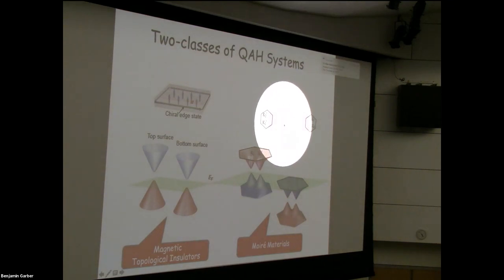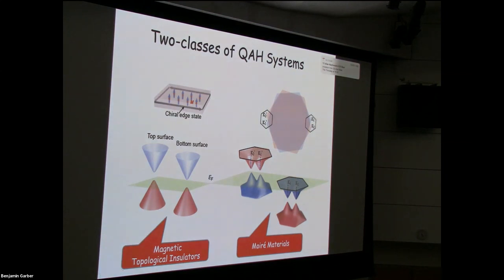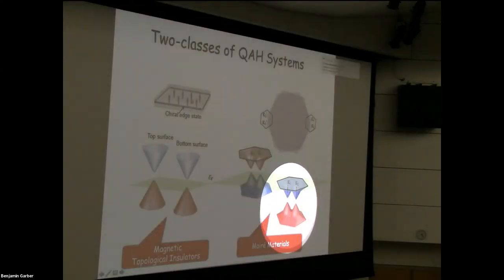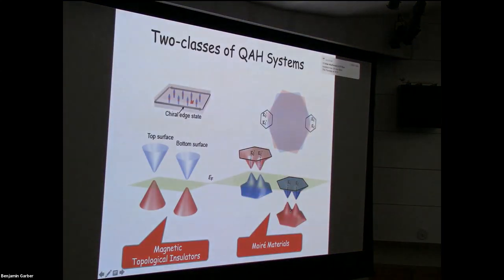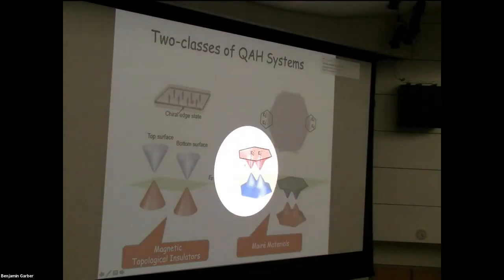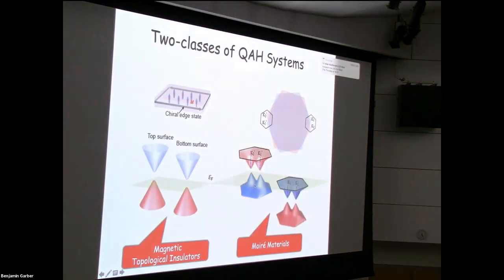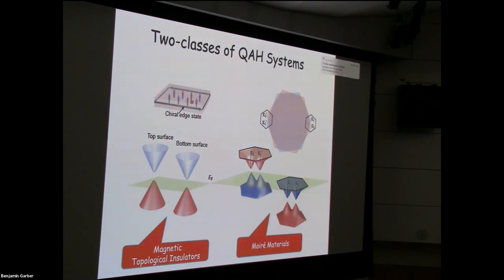What's going on in these twisted bilayers is different, and it's indicated by the cartoon on the right. There are two different valleys, two regions of momentum space. One of those regions, in the breaking of time reversal, both the valence band and the conduction band have been completely filled. They both have Chern numbers, but opposite Chern numbers, so they don't contribute to the anomalous Hall effect. Instead, the anomalous Hall effect comes from the other valley, and only the other valley contributes Hall conductivity, and it has two Dirac cones, one Dirac cone contributed by each valley, and so that's the nature of that quantum anomalous Hall state.